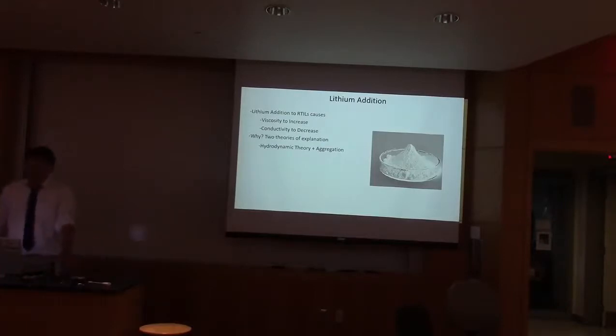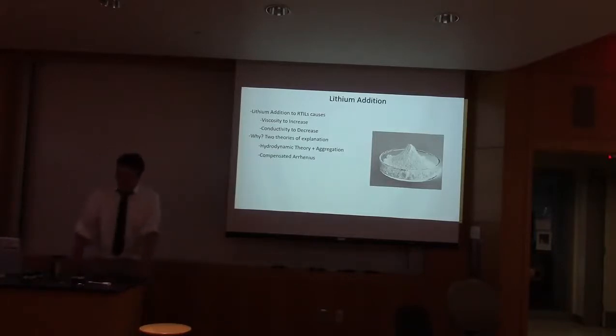There are two theories of explanation that I've been working with and that I'd like to cover in this talk. One is the standard, more canon model, which is hydrodynamic theory, which is related to the ability of these salts to aggregate in the presence of the room temperature ionic liquid. And then the compensated Arrhenius formalism is the technique and model that we've been trying to use to explain this observed increase in viscosity and decrease in conductivity. But first, I'll cover hydrodynamic theory to see the competition we're competing against.